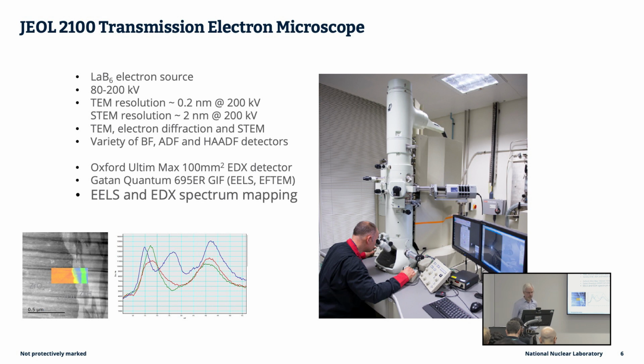The workhorse we've had in place for the last 10 years has been the JEOL 2100 TEM, equipped with EDX and EELS, which have enabled the application of chemical mapping in quite a lot of areas for us. Not as powerful an instrument as available nowadays, but it's equipped with a very good X-ray detector with a large solid angle, so we get a fairly decent count rate out of it, and spatial resolution down to a couple of nanometers if you're pushing it.